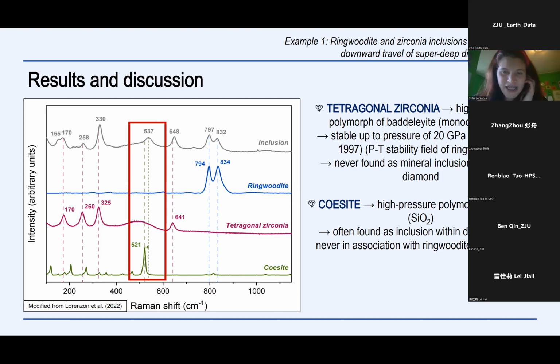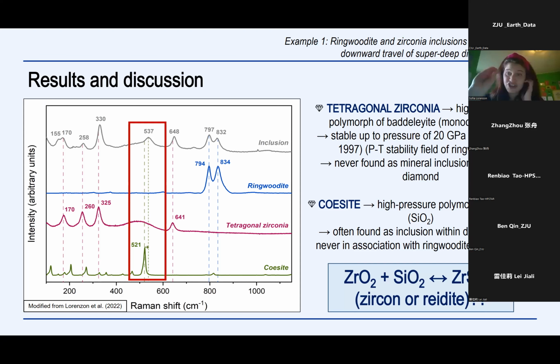However, the finding of tetragonal zirconia and coesite in contact with each other in the same multi-phase inclusion leads us, considering the chemistry of these two mineral phases, to suppose that probably these two mineral phases are the product of a reaction whose starting point was a former mineral, and this mineral was probably a zircon or a reidite. Reidite is the high pressure polymorph of zircon.